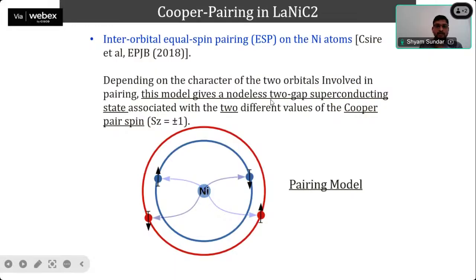this model gives a nodeless two-gap superconducting state associated with two different values of the Cooper pairing. So this Cooper pairing can happen in two different orbitals. This one is spin up, spin triplet, and this is again spin down, which is -1. So this is happening in two different orbitals. So the feature we are looking for is the nodeless two-gap superconductivity.